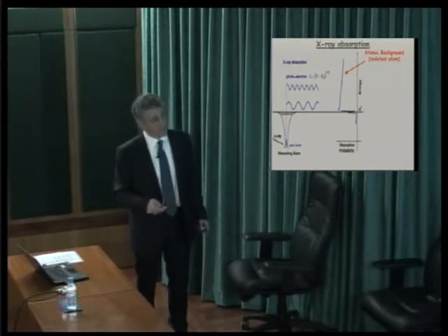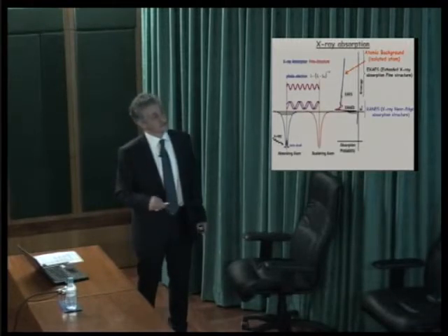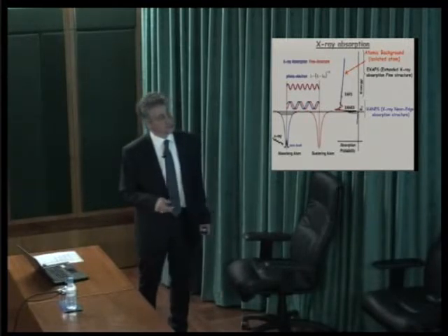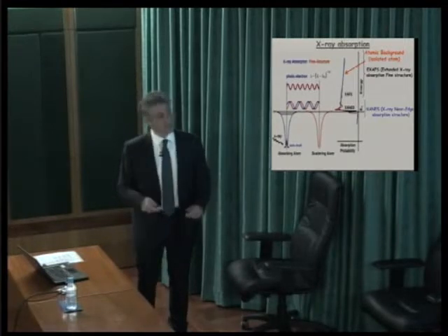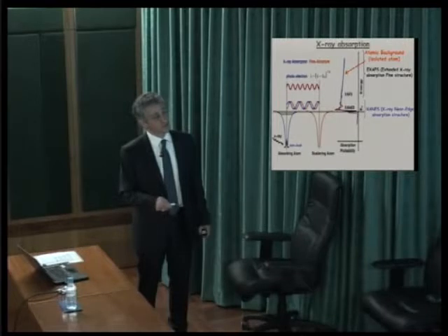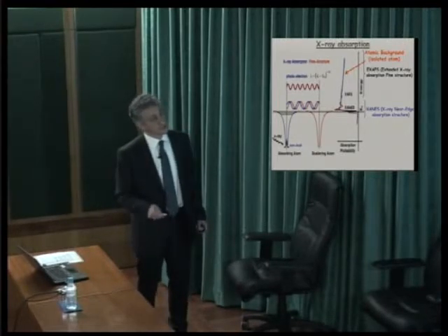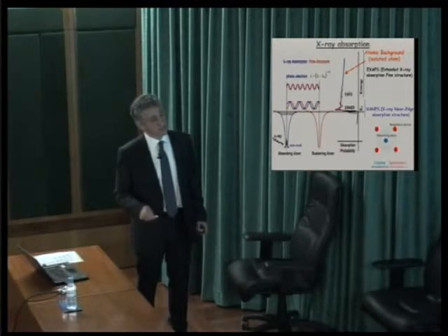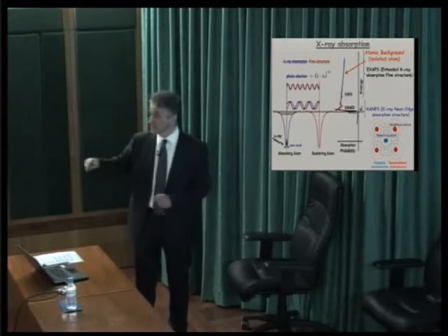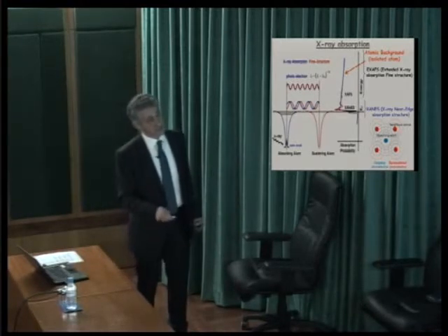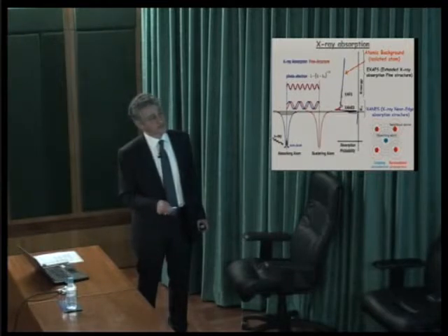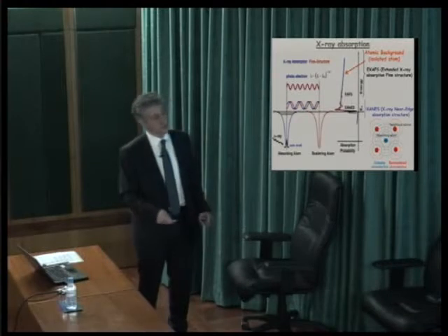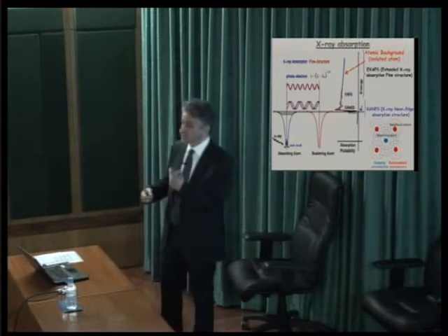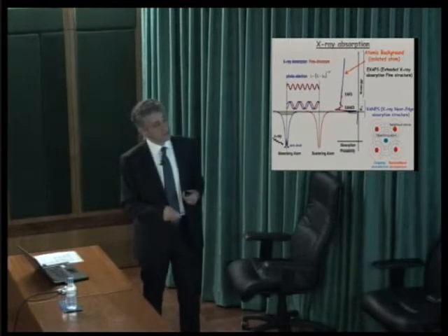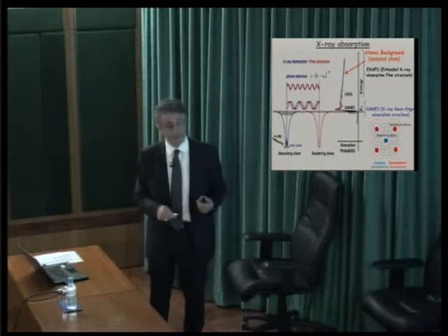Now, as soon as this atom has a neighbor, this is well described by quantum mechanics: quantum mechanical interference of the photoelectron wave with this well. You will have an outgoing and backscattered wave that interfere, and the interference is going to modulate the absorption cross-section. You can look at it pictorially, where you have an outgoing photoelectron wave and a backscattered photoelectron wave, like the waves in a pond of water, and they interfere and give rise to these modulations. It's easy to understand that if you perturb the system by a chemical reaction or a photo-induced process, and you change the bond distances between these two atoms, then the interference pattern is going to change, and therefore the modulations.